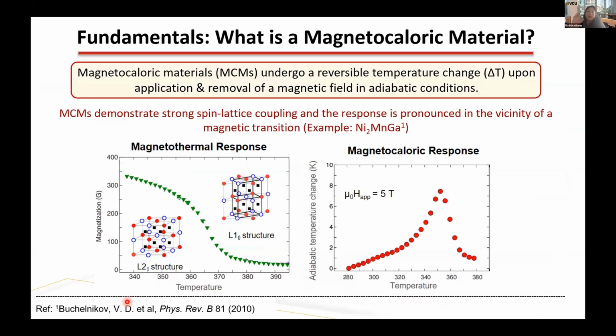A little bit of fundamentals on what a magnetocaloric material actually is. By definition, a magnetocaloric material is one that undergoes a reversible temperature change upon application and removal of a magnetic field in adiabatic conditions. Now, any magnetic material will do this - if you apply a magnetic field and remove it, it will undergo a temperature change. Even iron would do this, but the temperature change is very small. So to see a pronounced temperature change, the magnetocaloric material must demonstrate a strong spin lattice coupling, and typically this response is most pronounced when it occurs in the vicinity of a magnetic transition.